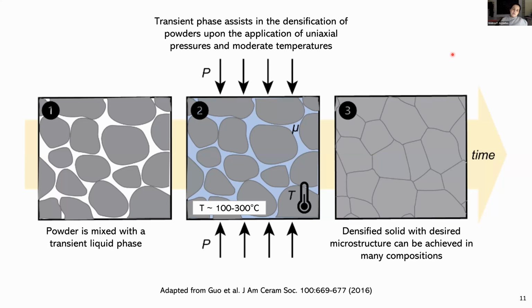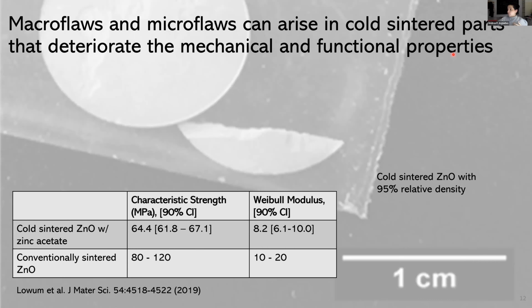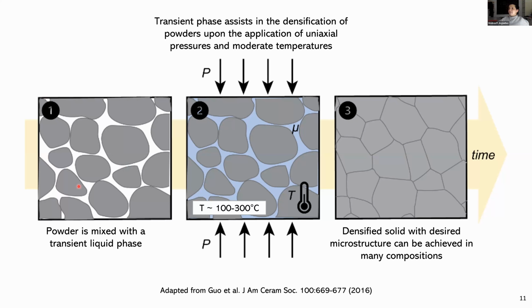In the cold sintering process, the objective is to bring these temperatures down significantly, hence the name, so that we can reduce the energy resources needed to sinter these materials. But also, more importantly, we can now combine different material types that were not compatible in a high temperature sintering process. So in cold sintering, the process looks something like this. You have a powder that you mix with a transient liquid phase. That transient liquid phase assists in the densification of the powders once you apply the uniaxial pressure, but still staying an order of magnitude lower in the temperatures that we need. At the end, you have a densified solid with hopefully the desired microstructure, and we can achieve many compositions. So that's all fine. But what is the challenge when we're using the cold sintering process?